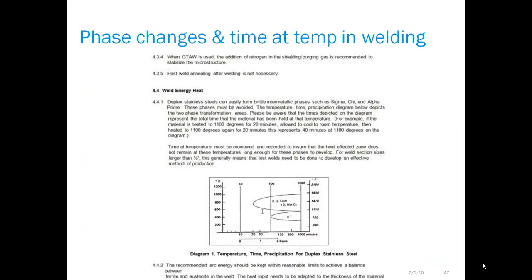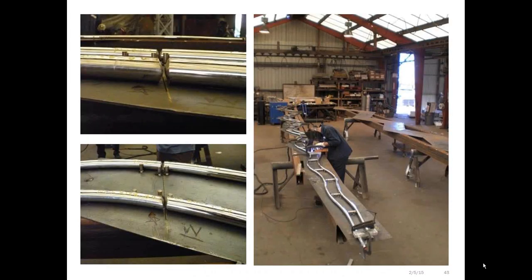So phase change, time and temperature. This graph comes out of that manual I showed you a moment ago. And what it's telling you, I won't bother you with trying to zoom in on it, is that we need to pass through that 900 to 300 C degree range quite quickly. We limit time at temperature to a matter of minutes in any of these welds. And it depends on how big the weld is, how hard that is to do. Some of these bars were 1.5 inches in diameter, and so we had a fair amount of monitoring to make sure we kept the time and temperature correct.